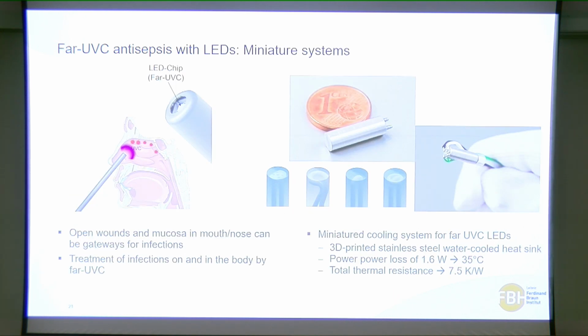So what can we do next? The LEDs are small and have a compact form factor, so the ideal way to use them would be to disinfect wounds on the human skin, and also mucosa in the mouth or in the nose. In order to do that, you need to make a miniature system, and as we all know, one of the big problems is removing the heat from the LEDs, so we have designed a miniature system here. It has a 4.5 millimeter diameter. We did this with 3D printing in stainless steel, and for a power loss of 1.6 watts, we get only 35 degrees Celsius, and a total thermal resistance of 7.5 Kelvin per watt. You can see here it's basically just an LED on the system, and we can very effectively remove the heat from the device. So that would be the next step in terms of irradiation.